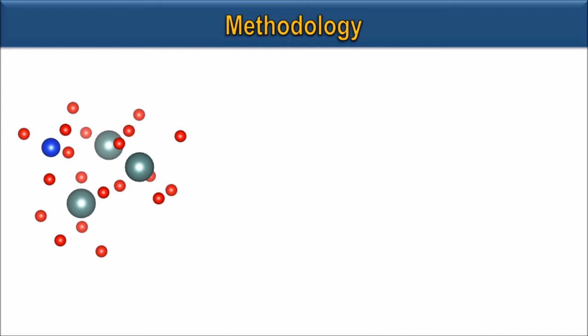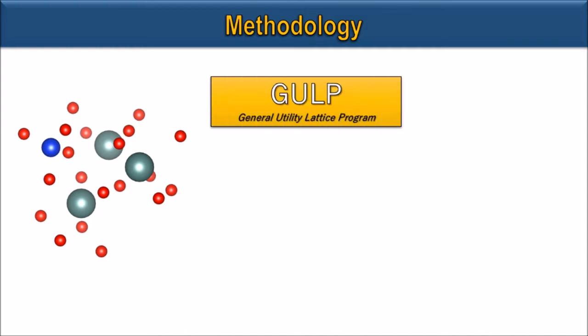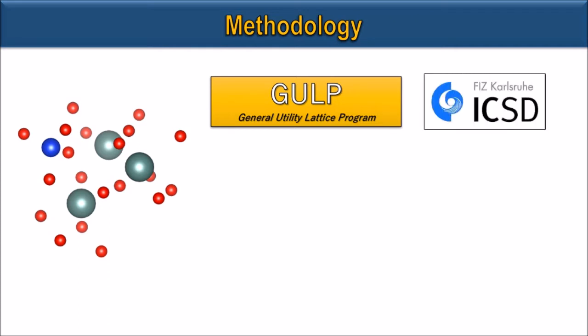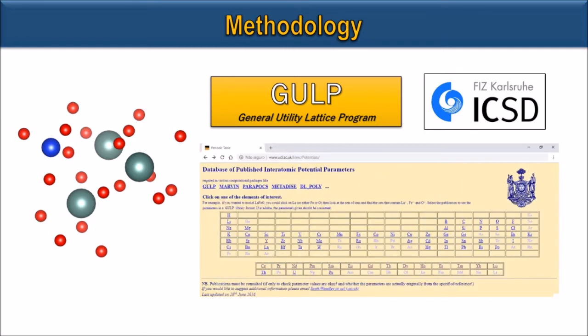So, talking a little about the methodology used in this work, the approach of choice for this study was classical and static computational calculations, where ions interact in the structures through interatomic potentials. For these calculations, we used the GULP code, and the lattice parameters of the structures were obtained from the ICSD database. The interatomic potentials were based on the database available on the website of University College London, which were empirically modified to reproduce the matrix with good agreement with the experimental data in the literature.